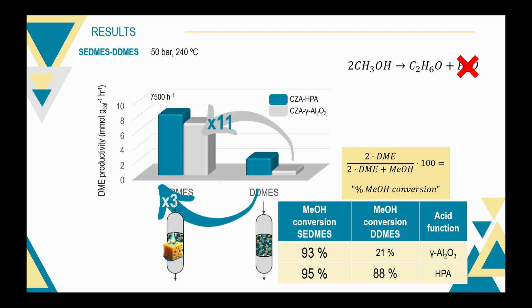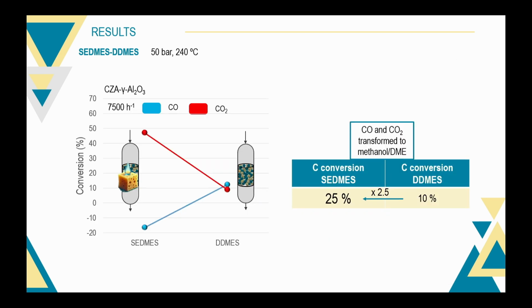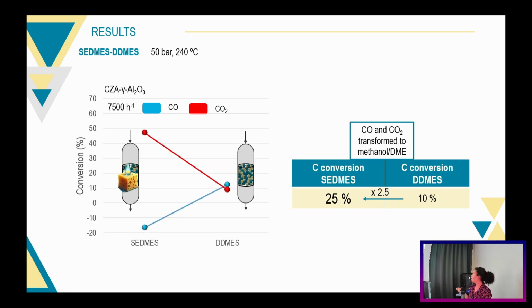So this meant that by removing water, we are preventing the gamma alumina from deactivating by water. But this enhancement alone cannot account for all of this increase in DME productivity. So we also calculated the total carbon conversion, understood as the CO and CO2 transformed into methanol or DME, for both processes and the gamma alumina containing bed.